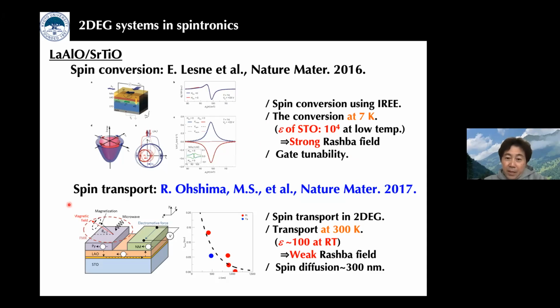So my group also used this system, but for another purpose, namely spin transport. As I mentioned, the dielectric constant of strontium titanate is quite large at low temperature, but the value largely decreases at room temperature. This means the Rashba field in the 2D system becomes very weak. In such a case, spin transport can be realized. This is what we expected.